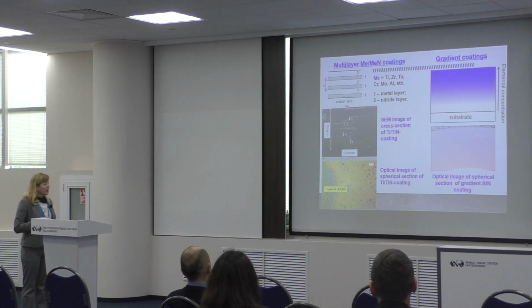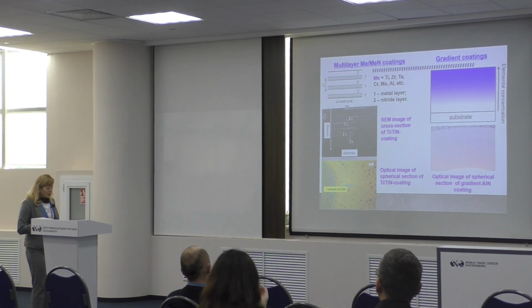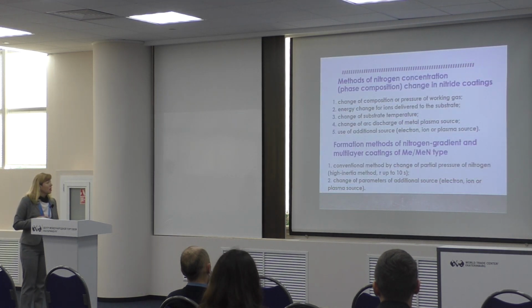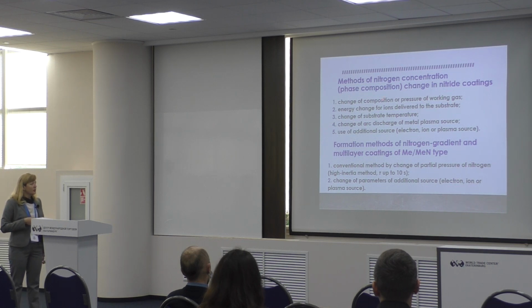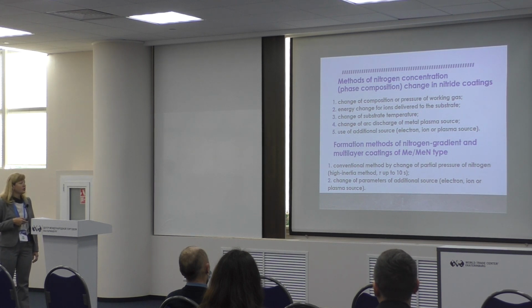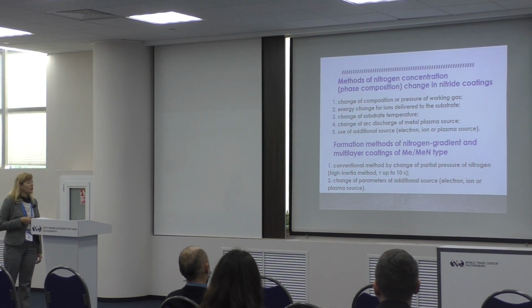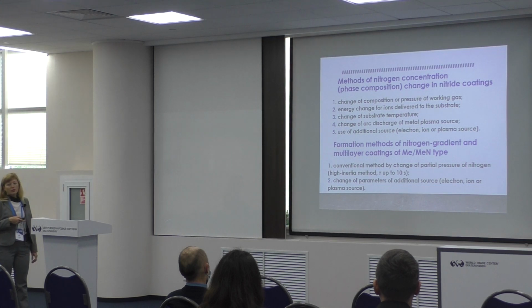And we can deposit gradient coatings with changeable elemental composition from the substrate to the upper boundary of the coatings. In this report, we change the concentration of nitrogen from the substrate to the upper boundary. Methods of changing nitrogen concentration or phase composition in nitride coatings are: change of composition or pressure of the working gas mixture, change of energy of ion delivery to the substrate, change of substrate temperature, change of arc discharge of the metal plasma source, or use of an additional source, for example, electron, ion, or plasma sources.